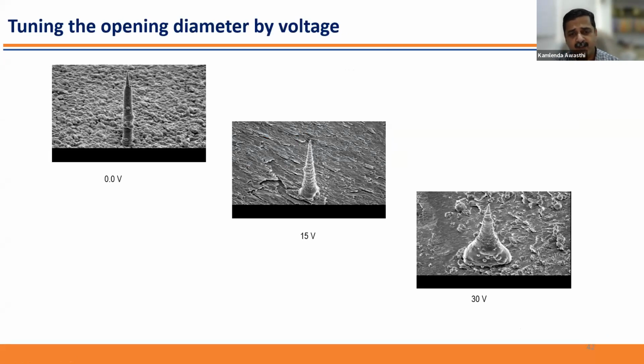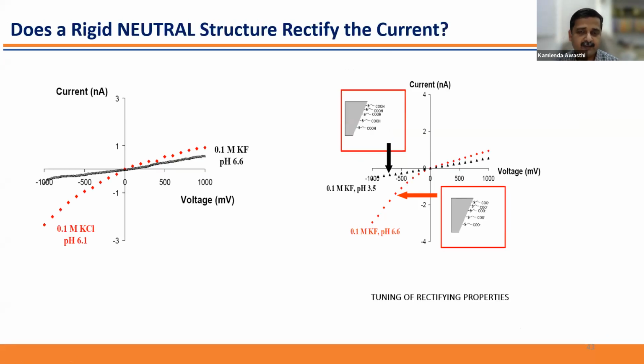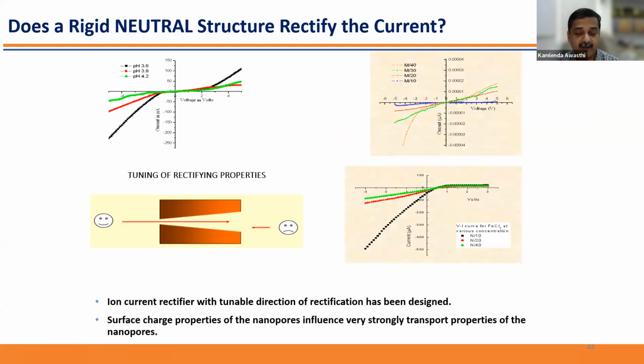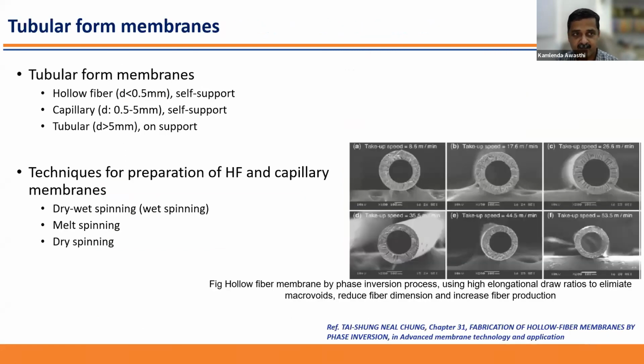We can tune the various shapes and sizes by the voltage also. And this is one interesting phenomenon: although the polymer is neutral, it shows a diode-like behavior in this membrane. This is because of various groups, such as carboxylic groups, present along the pore wall. So this is one reason for this rectification.